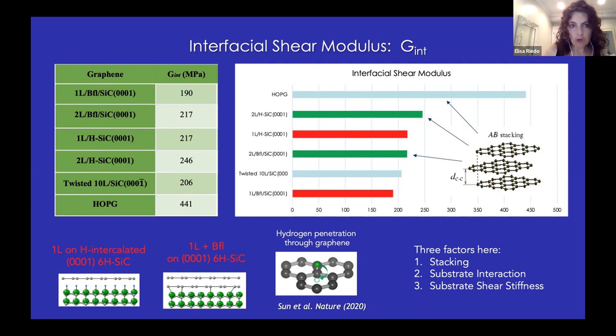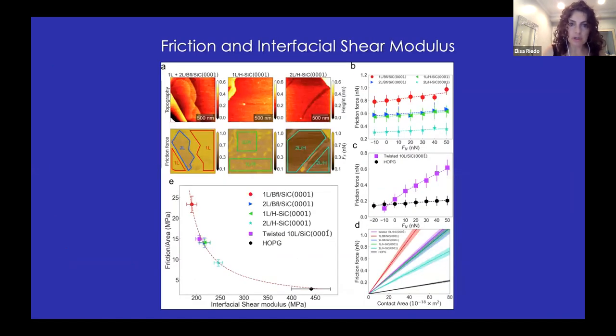That said, we moved on to understand the relationship with friction and dissipation. So we performed friction studies, atomic force microscopy friction studies, on the different samples. We plotted the friction versus normal load, and we looked into the friction coefficient. We started to see all sorts of differences for all the different materials. Then to compare them, since they have a different stiffness, we plotted the friction as a function of the contact area. And as you can see, the data gives quite good linear curves. And so then we extracted the slope of this curve, which is the friction per unit contact area. In this way, we were able to compare all the different materials, even if they have a different stiffness.